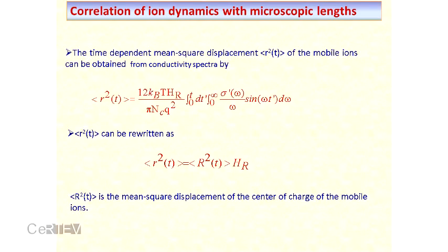Now I have tried to calculate some parameters from this linear response theory and correlate them to the conductivity, to see whether the conductivity or ion transport here depends on some structure. To show some structural connectivity, I have calculated these 2 parameters. One is a length scale, the displacement of the mobile ion at the crossover point. We can calculate it by taking a Fourier transform from the conductivity spectra. Another parameter is the long time behavior of this displacement, when the time is very high.